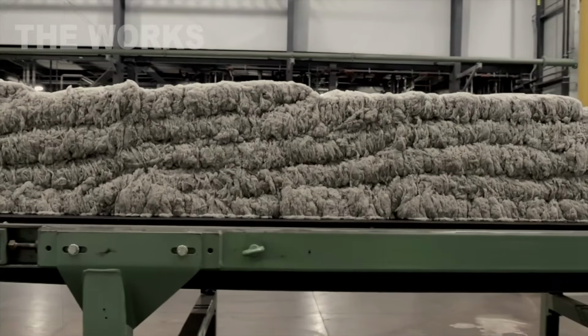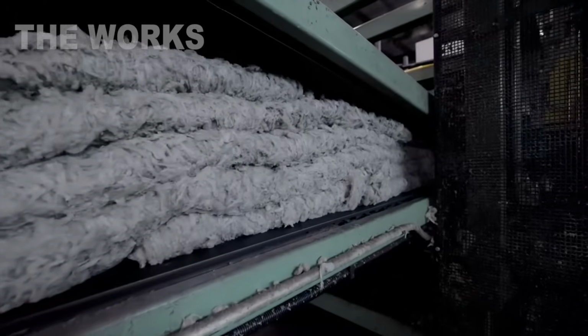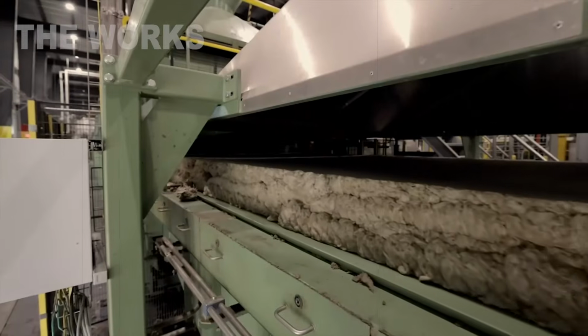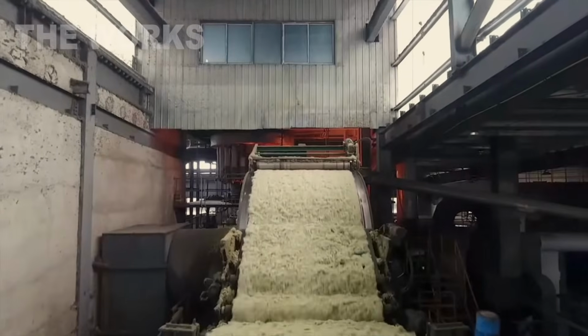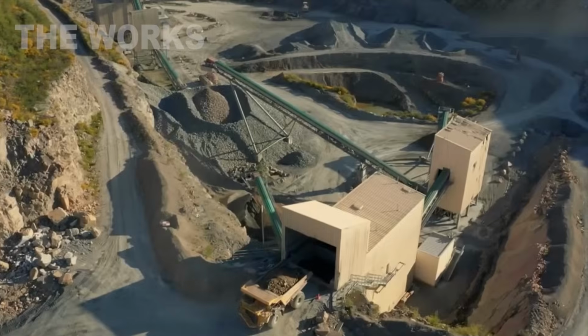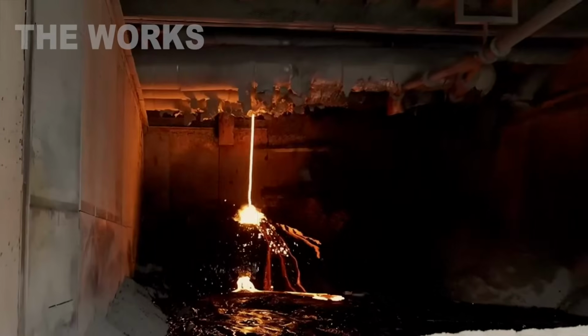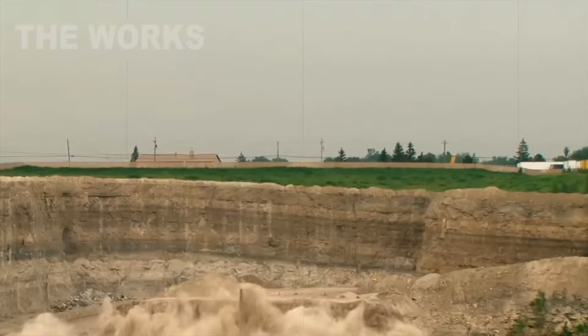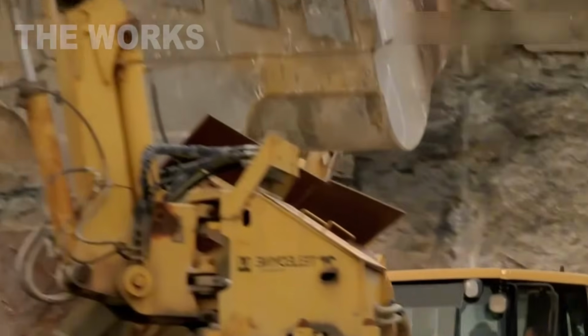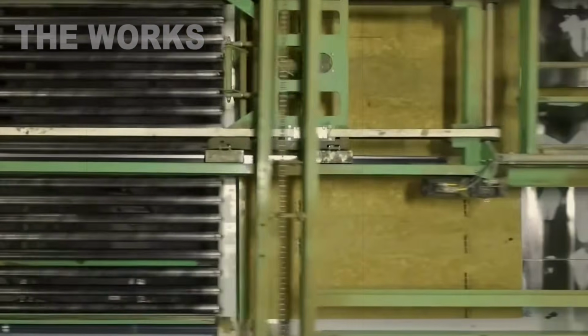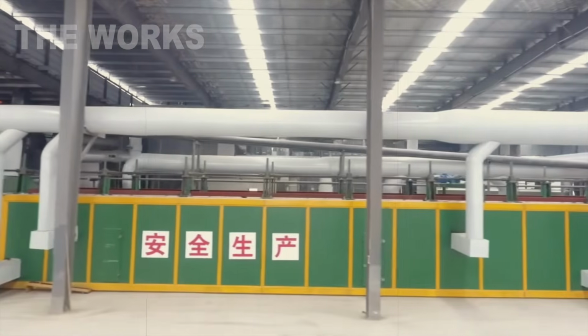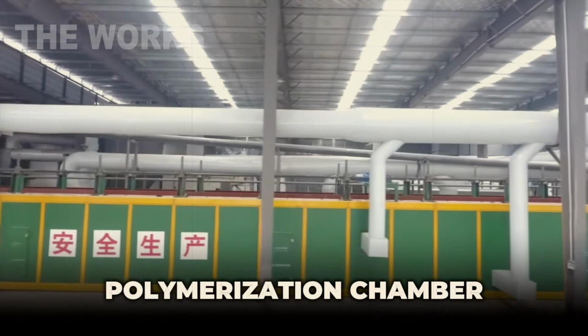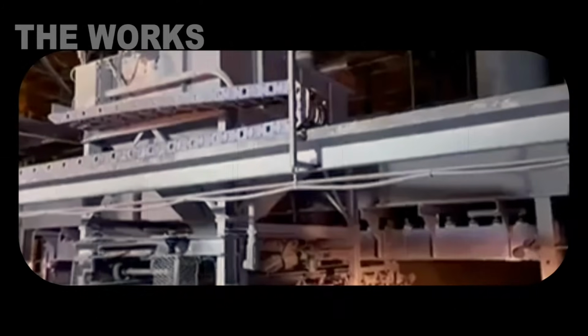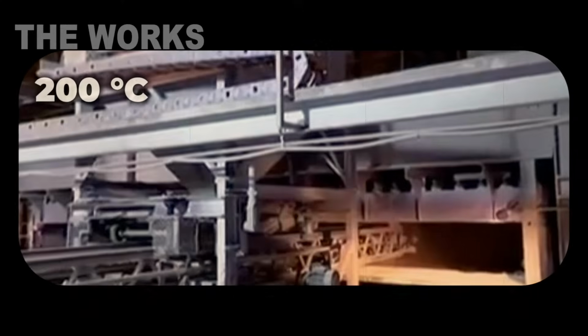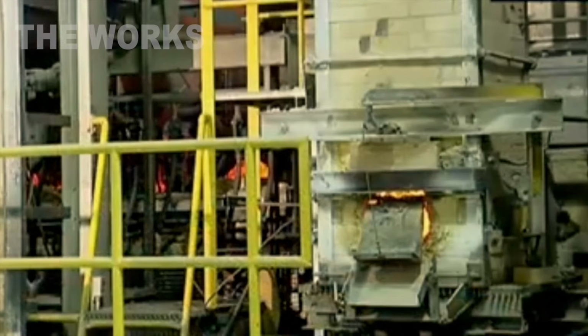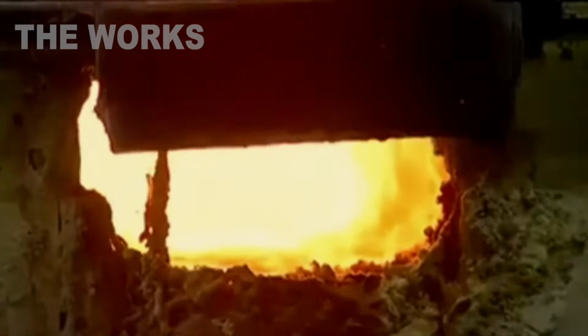And now this golden yellow fluffy carpet, reminiscent of a giant Swiss roll, is ready for the final stage, baking. It slowly enters an enormous oven known as a curing chamber. This is a long, multi-level tunnel maintained at a temperature of around 200 degrees Celsius. The purpose of this stage isn't merely to dry the carpet, but to bake the adhesive. Under heat, the resin polymerizes.